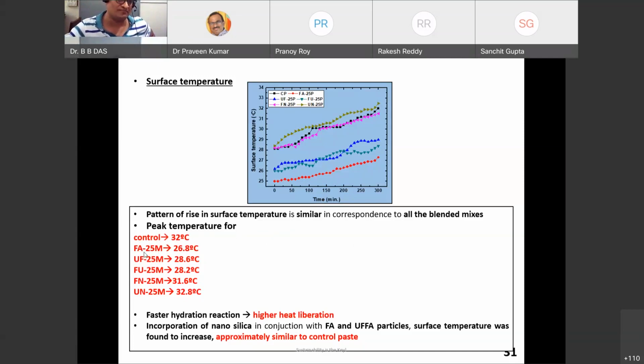Now, when I go with fly ash, ultrafine fly ash, both fly ash and ultrafine fly ash reduce the surface temperature tremendously. The peak temperature of the surface reduced. So imagine, the peak temperature is this much, 32 degrees for the control. Imagine the temperature that would have been happening in the core. That's why, whenever we go for mass constructions, fly ash is one of the key ingredients, because it lowers the temperature significantly.